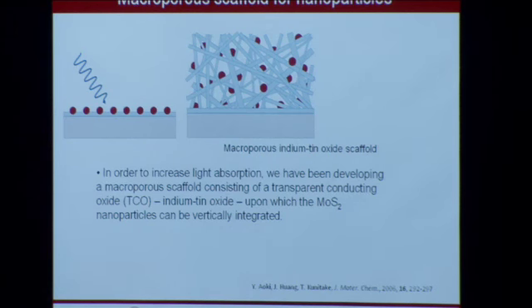So now this isn't quite enough because, as I mentioned, this is still a sub-monolayer of nanoparticles. It's not a lot of material, so when you shine light on it, you're not going to get that much light getting absorbed by your semiconductors. So what we've been doing instead is taking these exact same nanoparticles and impregnating them onto a three-dimensional scaffold that we synthesize by sol-gel chemistry. We literally make a sol, we use a piece of filter paper as a template, we burn off the filter paper, and we're left with a macroporous structure of indium tin oxide sitting on top of glass.